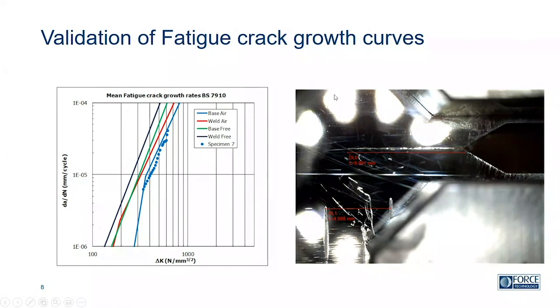On the right, you have the photographic image of how we measured the crack growth during the test. I think we took photos, I don't remember if it was every 10 minutes or something. Before we started the test, we had made some scratches with a distance of 5 millimeters for reference. And then we could calibrate our measurement software. And then we measured the crack growth at different time intervals.